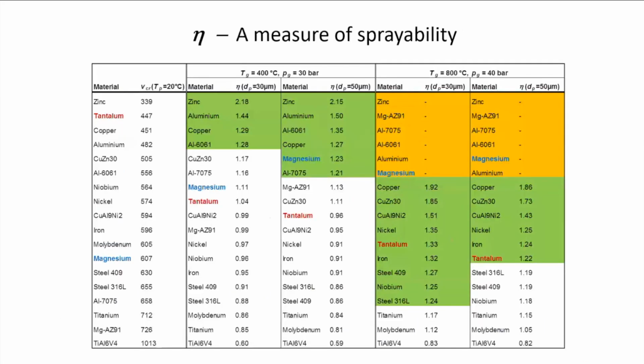Now, if I wanted to squeeze the entire cold spray research that I was involved with into one slide, that would be it. Eta should be taken as a measure of sprayability. Before, we thought that critical velocity is the measure. So we want to decide whether tantalum is easier to spray or magnesium. We look at the critical velocity, we see that for tantalum it is less than, and for magnesium it is more than 600 meters per second. So we say, oh, magnesium is more difficult, but that's not the case. When you say which one is easier, you should not only look at the material, but also at the process settings or the equipment.